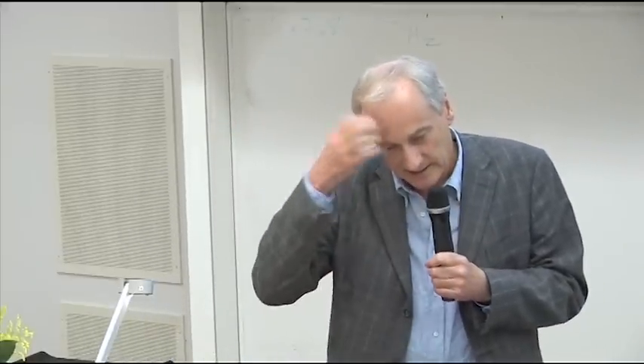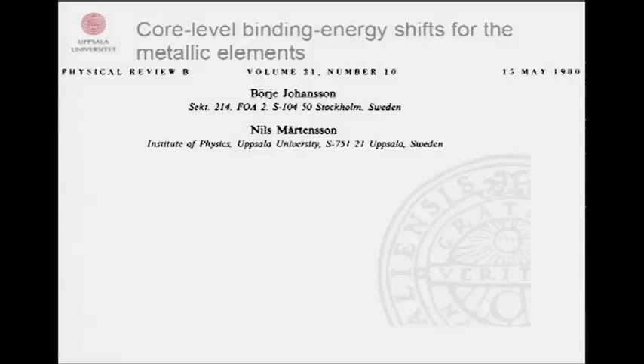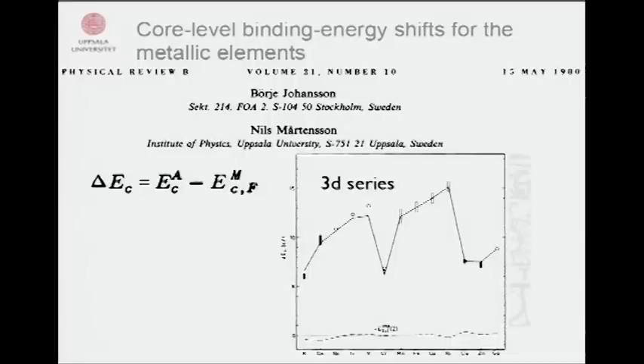And then accidentally, one year after this paper was published, which was on the core level binding energy shifts for the metallic elements, this was the work that Börje and I were spending much of our time on at that time. We were looking at the shifts between the core level in the atom, as you measure it relative to the vacuum level, and for metals, as you measure it relative to the Fermi level. And we got really excellent agreement in these cases. If you compare to what was around, it's almost 10 times better.